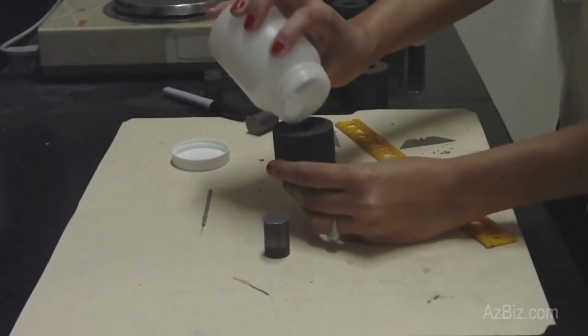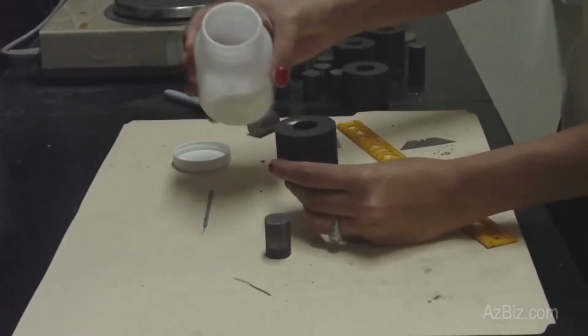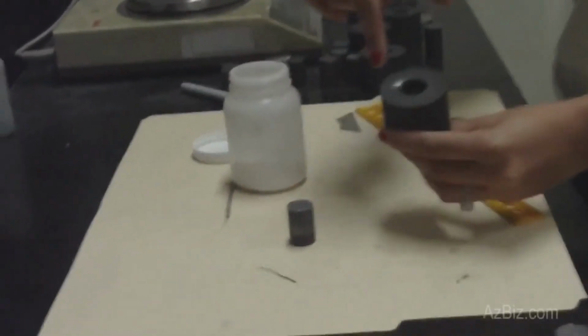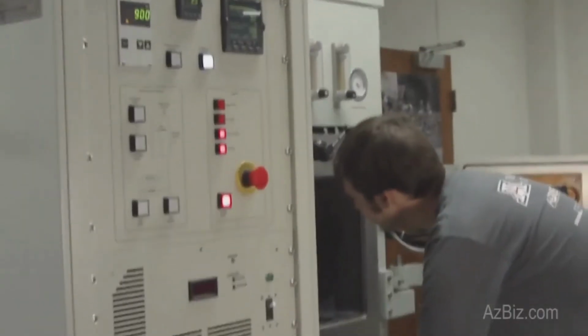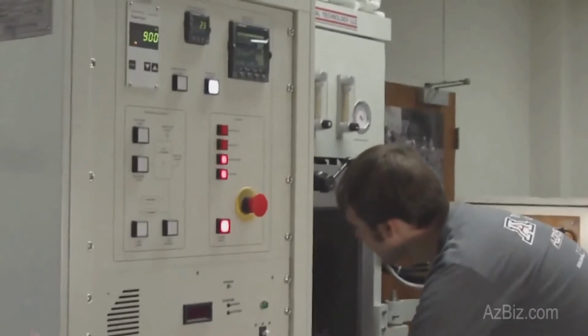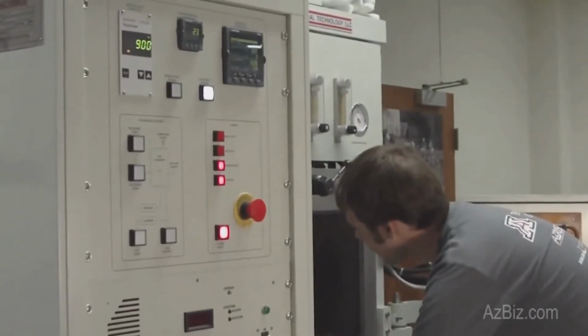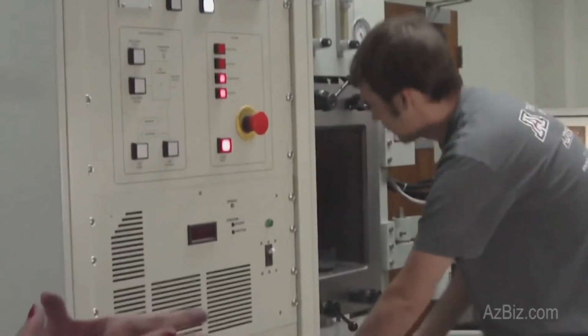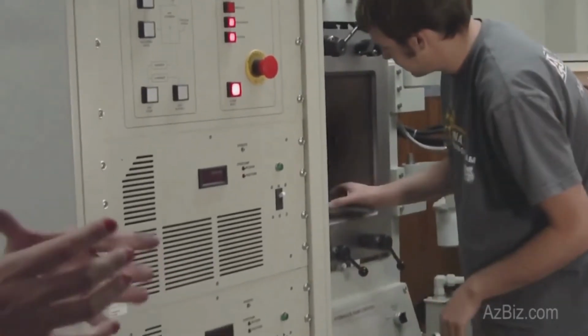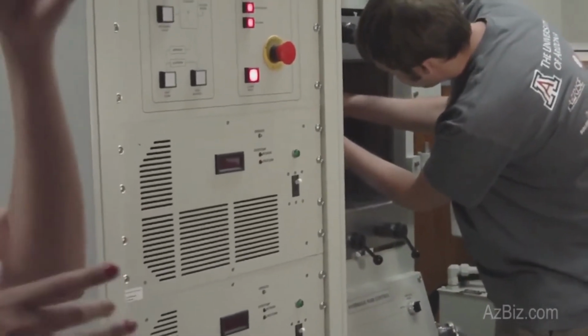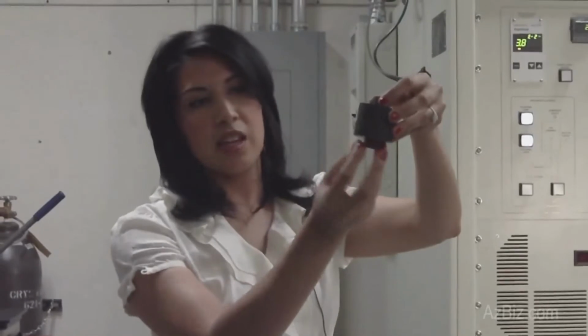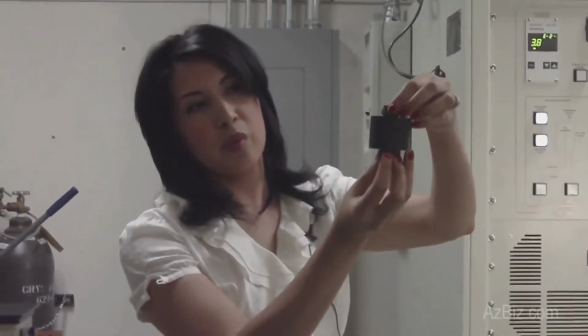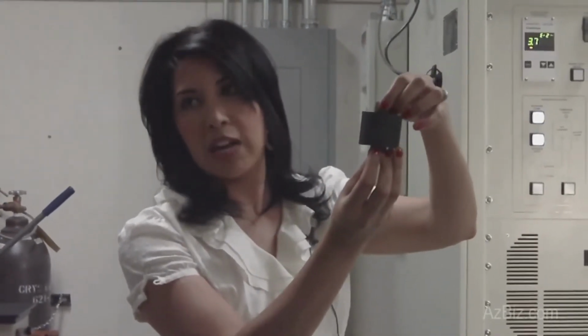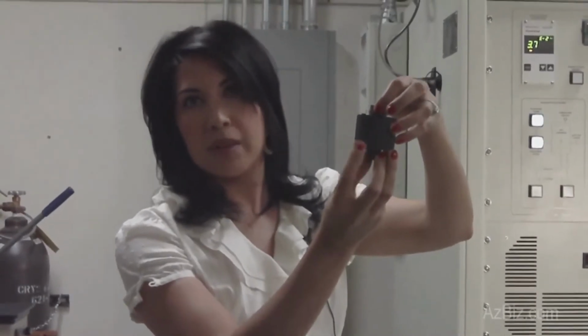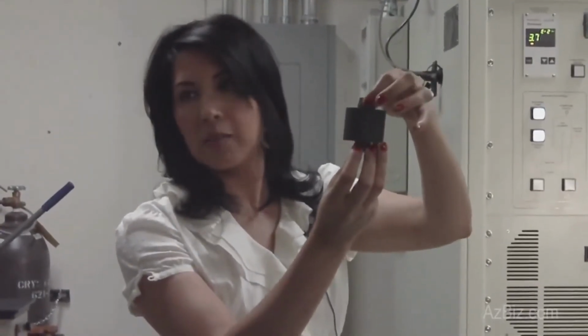Pour it in the die, but a lot goes into making this powder before we actually fill it into the die. So right now we're aligning the die punch assembly with the powder in it so that it makes contact with the spacers and then the electrode. This is what's inside the furnace right now, and these punches are going to get really bright, and then this will start to warm up, and then this will obviously get as bright as the punches.